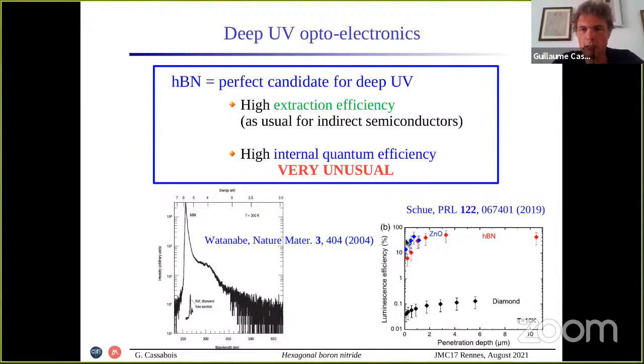Recently, our colleague at ONERA, in the group of Julien Barjon, managed to quantify this, and they compared diamond, HBN, and zinc oxide in terms of luminescence efficiency. They measured that HBN has a luminescence efficiency comparable to a direct semiconductor like zinc oxide, and much higher than diamond, as previously demonstrated.